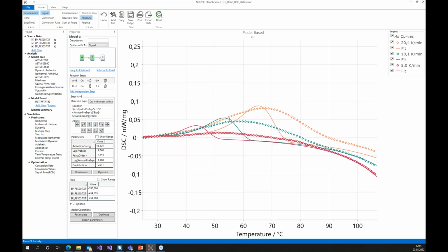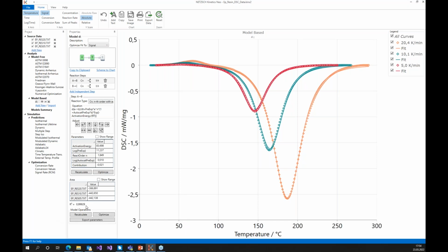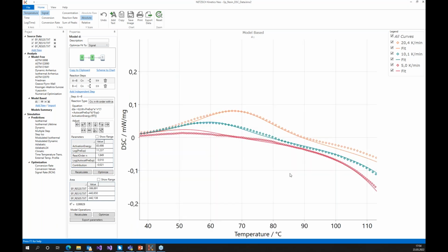Now we have this position for the first peak and make optimization again, and see what happens. Now the software makes optimization for the whole model for all reaction steps, and as a result we have R square of 0.9993, and here is a really good fit between the experimental data you see and our simulated data.